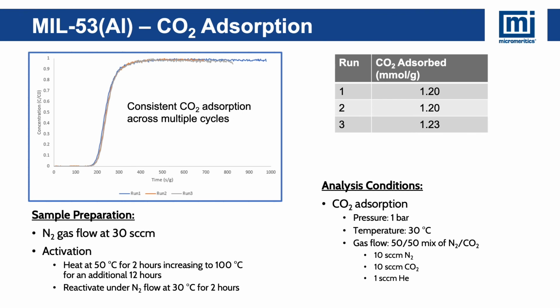Next, we'll move on to the MOFs. The first one, which is MIL-53 aluminum. We can see very consistent CO2 adsorption across multiple cycles, such that we're able to easily reactivate this material without any heat. However, this material did adsorb the lowest CO2 across all cycles.